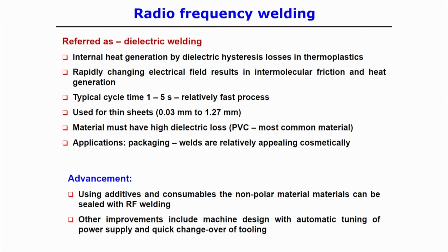Here the typical cycle time is 1 to 5 seconds. Therefore, we can say it is a relatively fast process as compared to other existing processes. It is used for very thin sheet, 0.03 millimeter, but a maximum of 1.27 millimeter sheet can also be done using this technique. The material must have high dielectric losses, then only this process is applicable. For example, PVC, the most common material, is generally joined by the radio frequency welding process.